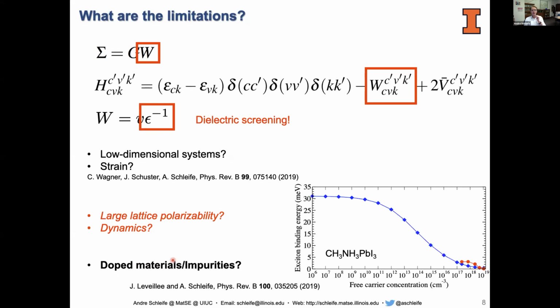Before we go there, I want to point you to another example where screening is critical, or more precisely, where the description of screening is potentially challenging, and those are doped materials. So if you have a semiconductor, for instance methylammonium lead iodide, and you dope this material, let's say we n-dope it, meaning we introduce free electrons in the material, those free electrons can also respond to an external electric field. And so in this response function picture that Frank really nicely described earlier today, that response of the free electrons has to be taken into account, because this dielectric screening, or this dielectric tensor, is nothing other than a response function. And if the electrons due to doping affect the response, it would have to be taken into account in the modeling of the screening.